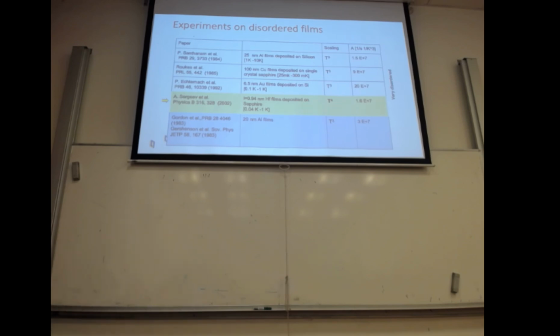And then I started to look at what is the typical relaxation time that the experimentalists measured. And I found out that when they consider very thin films that are very disordered, only Gershenson found a T4 temperature dependence as one would expect. All the others basically found the temperature dependence of the clean case, with T cube, even if the film is really very disordered. And actually there was an estimate from a 20 nanometer aluminium film that was done by Gordon. And basically what I see is that this value doesn't agree with the theoretical value that Reiser found, because he found that it is actually bigger.